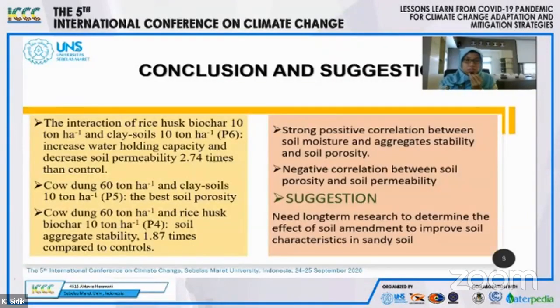Conclusion and suggestion. The interaction of rice husk biochar 10 ton per hectare and clay soil 10 ton per hectare, P6, increases water holding capacity and decreases soil permeability up to 2.74 times compared to the control. Cow dung 60 ton per hectare and clay soil 10 ton per hectare is the best for increasing soil porosity. Cow dung 60 ton per hectare and rice husk biochar 10 ton per hectare is the best for soil aggregate stability.